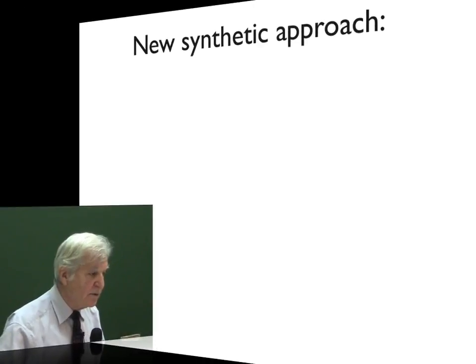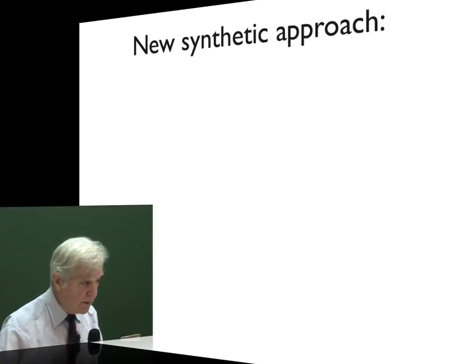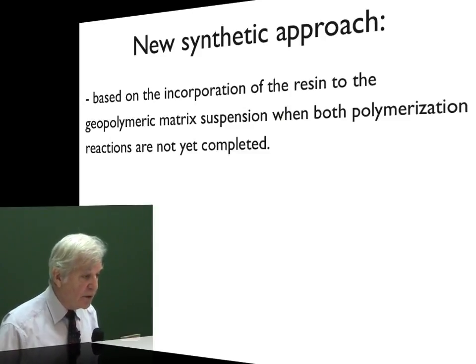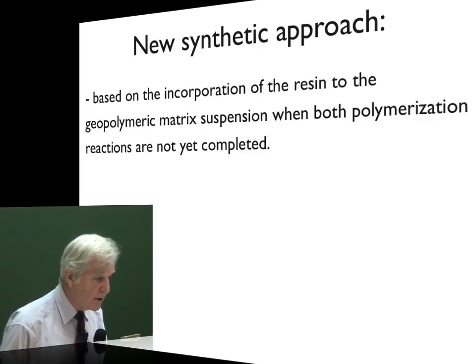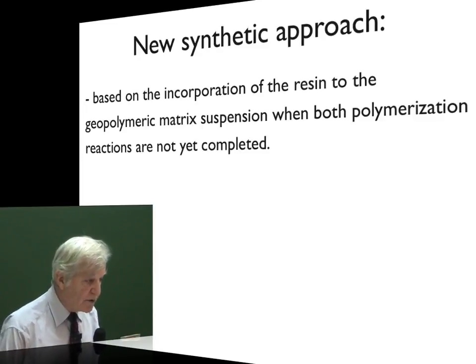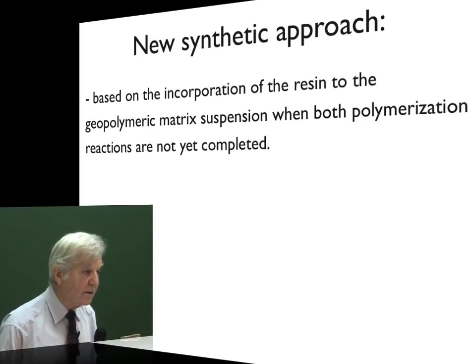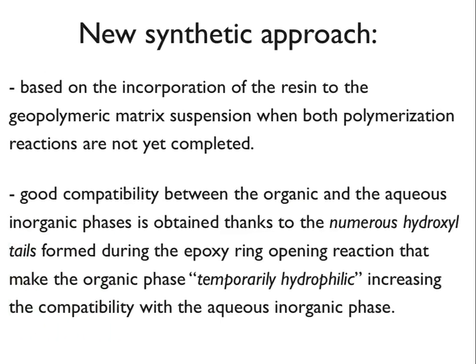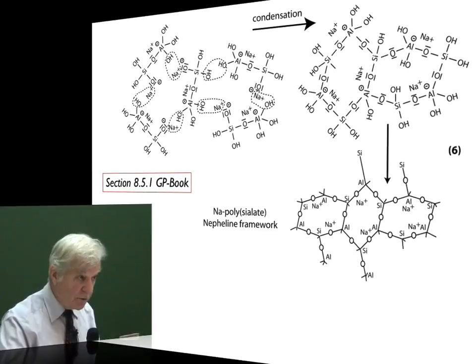What is this new synthetic approach? Well, it is based on the incorporation of the resin to the geopolymeric matrix suspension when both polymerization reactions are not yet completed. Good compatibility between the organic and the aqueous inorganic phases is obtained thanks to the numerous hydroxyl tails formed during the epoxy ring opening reaction that make the organic phase temporarily hydrophilic, increasing the compatibility with the aqueous inorganic phase. I show you a sketch.